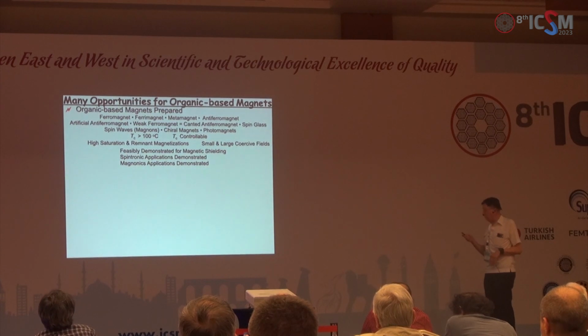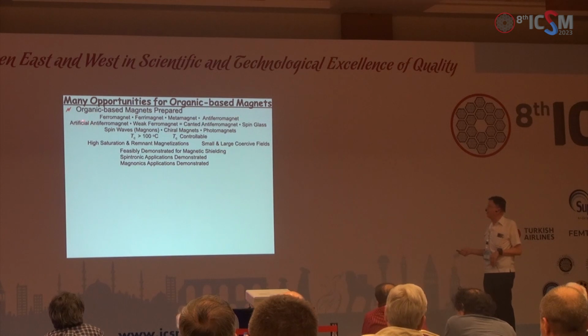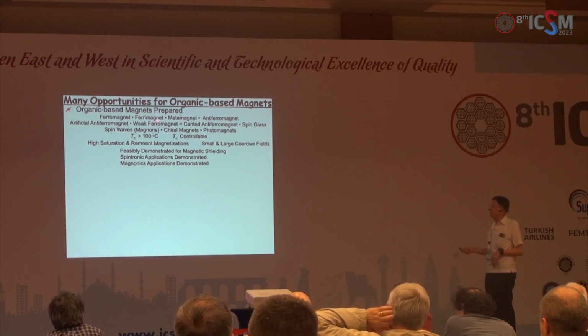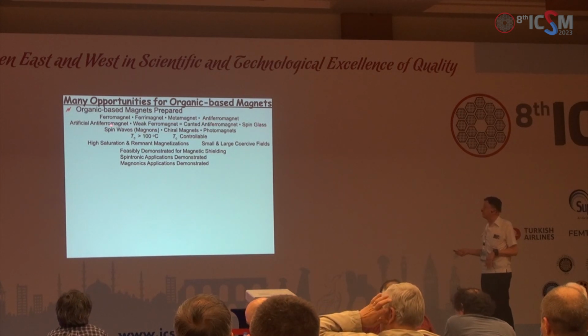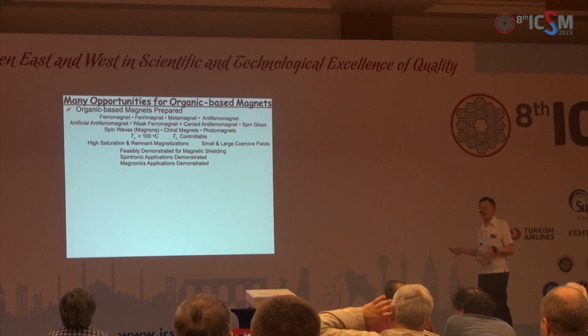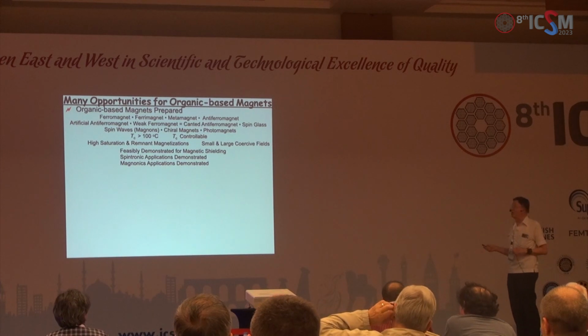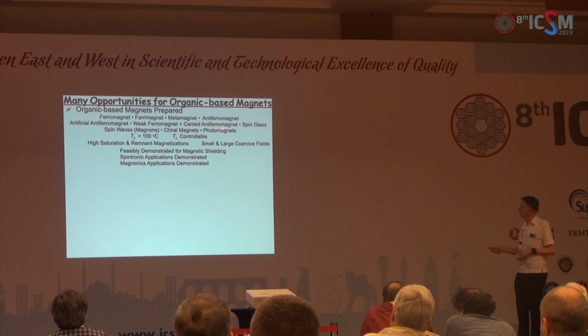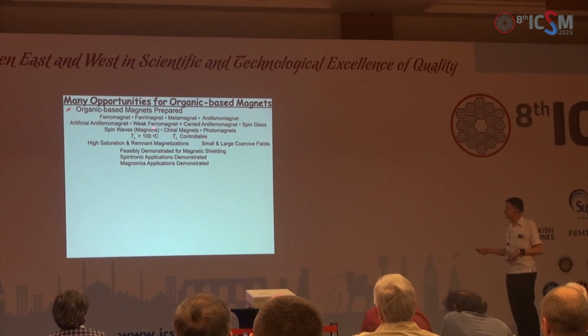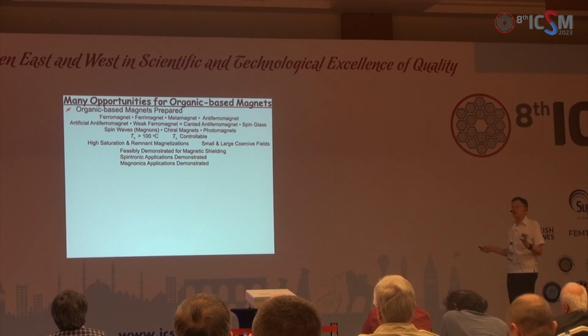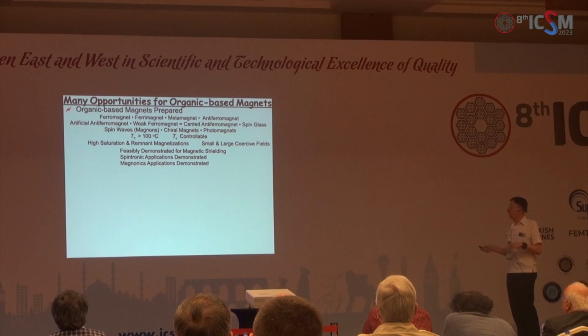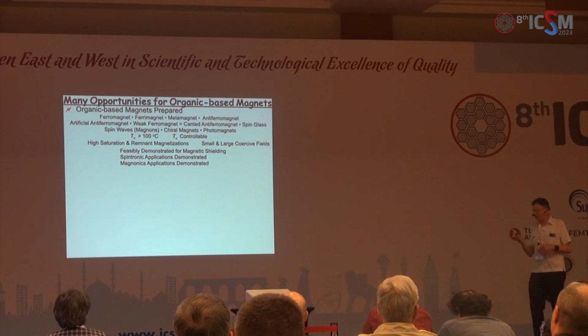I want to point out that you can make ferromagnets, ferrimagnets, metamagnets, antiferromagnets, artificial antiferromagnets, weak ferromagnets—which are also canted antiferromagnets—spin glasses, we see magnons, chiral magnets. One of my friends will give a talk on photomagnets, with ordering temperatures well above 100 degrees centigrade, controllable high-low saturation magnetizations, high-low coercive fields, and we've demonstrated a variety of applications in our own lab.